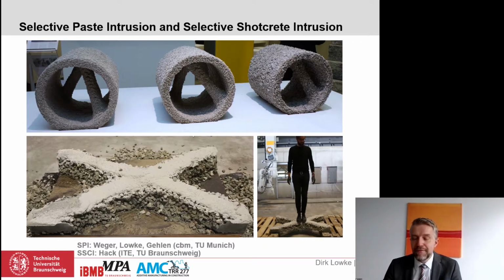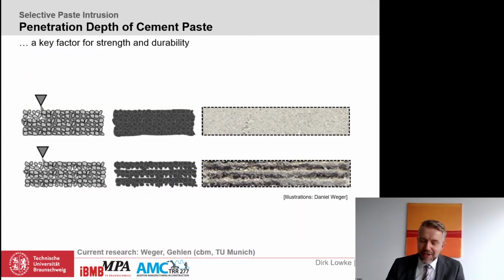As you can see, the first results are quite promising in terms of mechanical strengths, because the printed structure can easily carry a normal man's weight. I'm sure you will see more from this in the coming months. So what is the main challenge in selective paste intrusion or selective shotcrete intrusion? It is similar to the selective cement activation technique, since the fluid phase has to completely penetrate the layer thickness to ensure proper layer bonding.